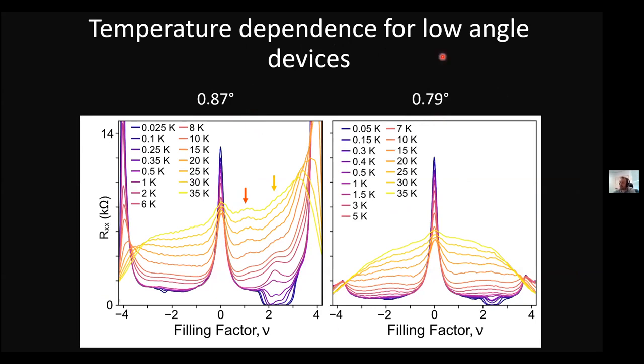So you can see for 0.87, as you raise the temperature, you kind of recover this peak in the resistance, so your correlated insulating state around half filling. Then you can even recover something at 1/4 filling. But here it's questionable whether you see and how much of the peak you can see around this. But I'll comment on this later on. Both of these devices, again, show this linear in T dependence. So in that context, they behave as the magic angle graphene.